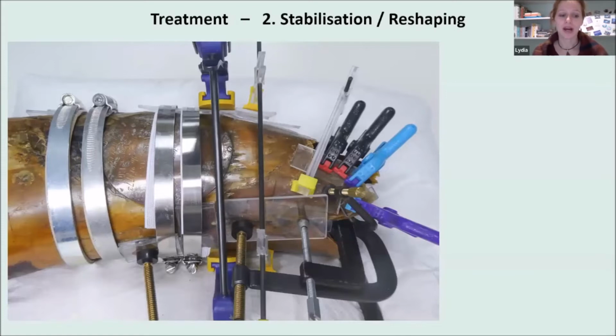While the horn was about to dry and the horn material was still flexible, I immediately started the reshaping and stabilisation process. Both processes are intertwined, as they have the necessity in common to soften the horn material prior to any intervention, to make it flexible and responsive. I achieved this through humidification by simply applying a moist fabric onto the horn surface. Depending on the task and thickness of the horn, I humidified areas between 2 hours for the laminating areas, 16 hours for compact and sturdy areas which are heavily deformed.